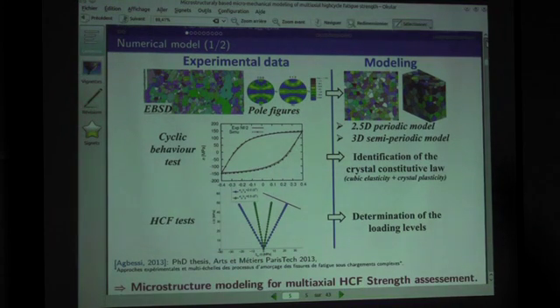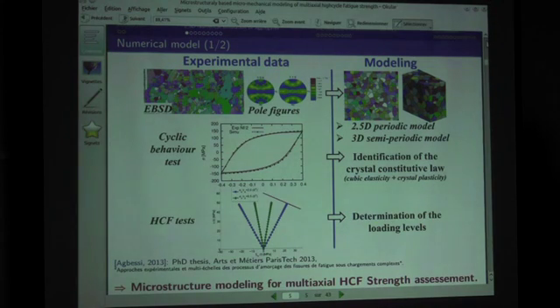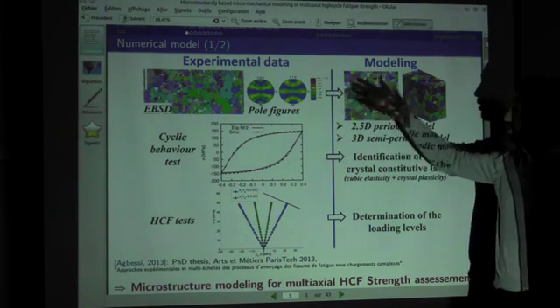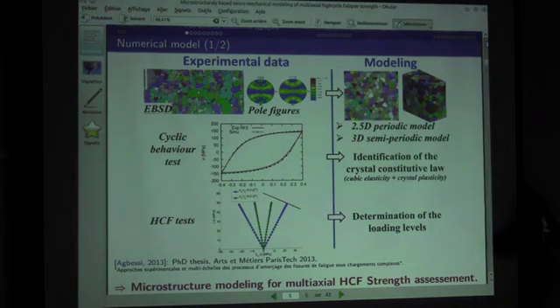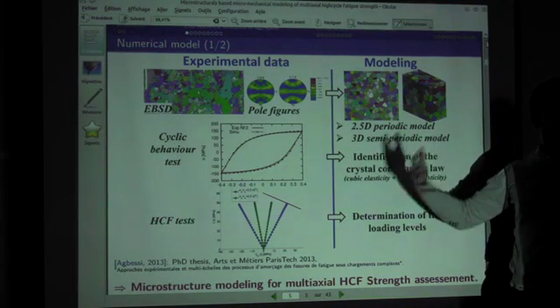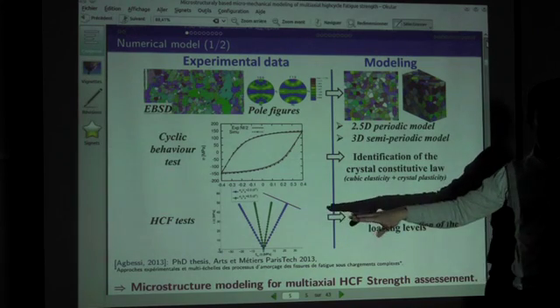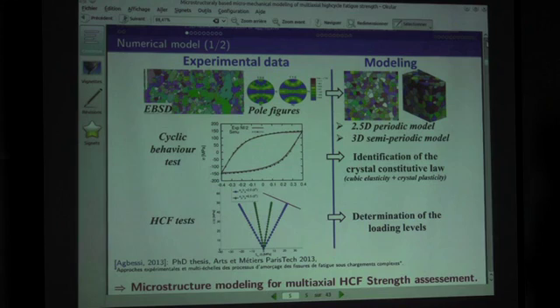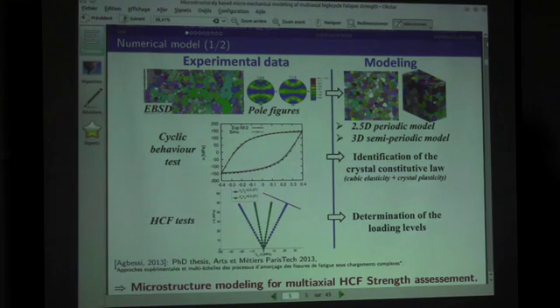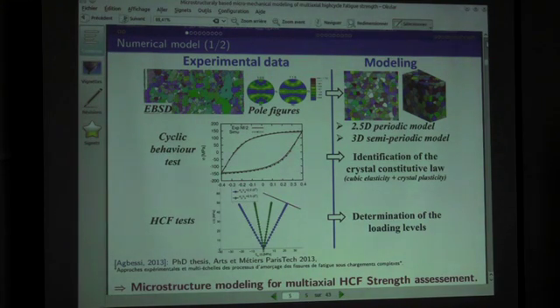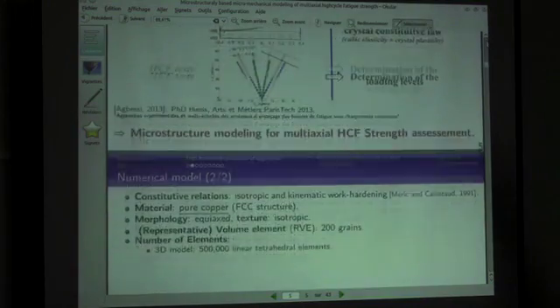What we are doing is based on microstructure modeling with two parts. One part is dedicated to obtaining experimental data from the microstructures, the EBSD for example, to identify clearly the microstructures and the cyclic behavior of the material, and then HCF tests, as we all do, to have the macro results of the behavior of the material with respect to different loadings. In parallel, we do simulation of 2D or 3D microstructures, and we use those data to build microstructure-sensitive parameters, at least a methodology that uses standard criteria but introduces sensitive aspects to the microstructure. So that's what we are trying to do.